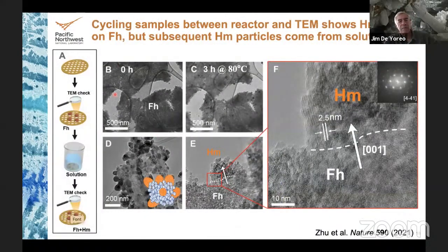So Guamin Zhu, my student, who did this work, first took indexed TEM grids. He put ferrihydrite on the grids and brought them back and forth to the reactor in the TEM and went to the same location to see what was going on. And what he found, if he fixed the ferrihydrite on the grids, is that the only place hematite could ever form was where the ferrihydrite was. And so the ferrihydrite is required, either by conversion or heterogeneous nucleation, to start the hematite formation.